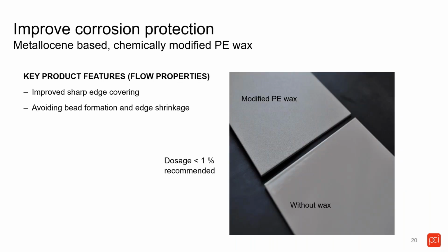A couple slides ago, I mentioned edge covering, flow properties. So this wax, now we do have a spray booth. We're not spraying complicated parts, three-dimensional parts, furniture, or anything like that. We're basically just spraying flat panels, but yet we're still observing how the edges will flow and how the edge will get coated and covered. And also we've seen commercial experience that's proven that this wax is pretty good when it comes to edge covering and flow, because it just modifies the flow properties to where you get better edge covering. So like it says here, avoiding bead formation and edge shrinkage. In addition to being PTFE free and not having to worry about that regulation, you get obviously some other benefits as well.